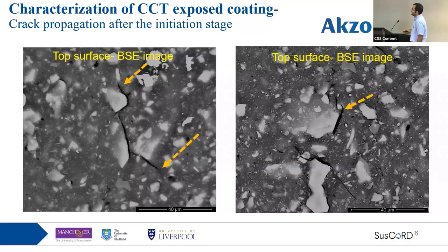And after the initiation, how the crack propagates will depend on different parameters and factors. Different rules will be followed, depending on the stress intensity factor of the crack. As you can see here, it seems like these cracks have already started to propagate, and the tip looks very similar to the tips of the cracks that are propagating through the coating. But this is probably at the early initiation of the crack that is going to propagate through the coating.